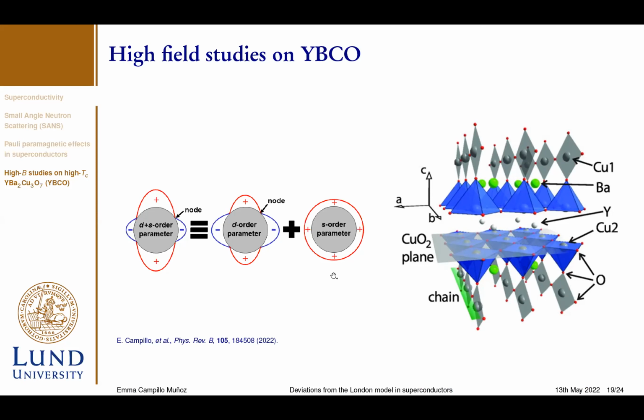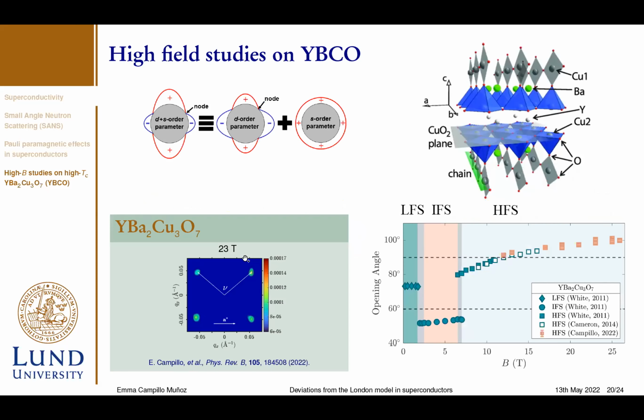When we combine these two contributions, we end up with a superconducting gap which has both S wave and D wave contributions, and the nodes will move depending on how strong the D wave superconductivity is in the sample, depending on the field that we are applying. In the past, the form factor and the vortex lattice of YBCO have been studied up to 16 Tesla. Three different structural transitions were first reported: a low field transition, an intermediate field transition and a high field transition. We think these transitions are related to the anisotropy of the London penetration depth along the AB direction.